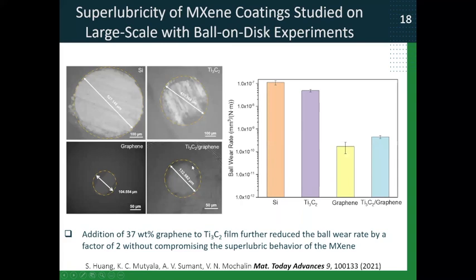For example, addition of graphene also reduces wear of the ball. So this is the wear of the ball which was rubbed against the MXene coating. This is against silicon, of course, very large wear. MXene less, but still quite large. When we add graphene, the wear becomes very small. So the data are also shown here.